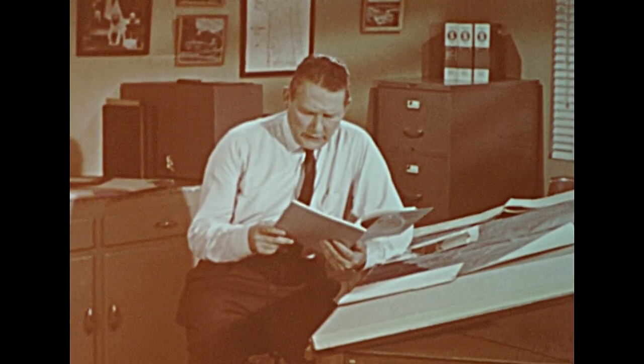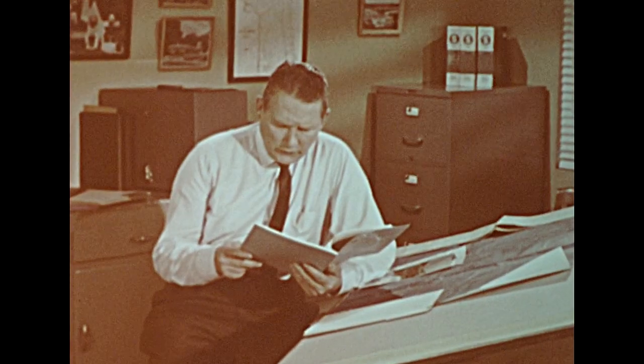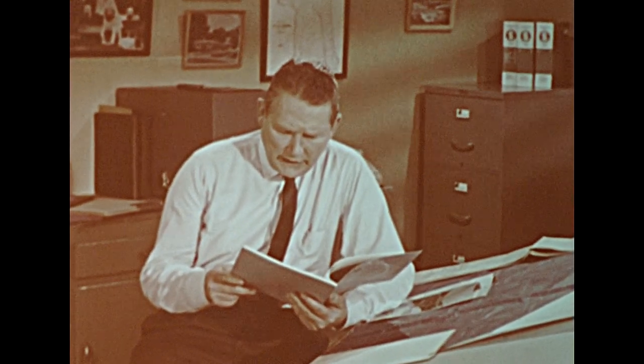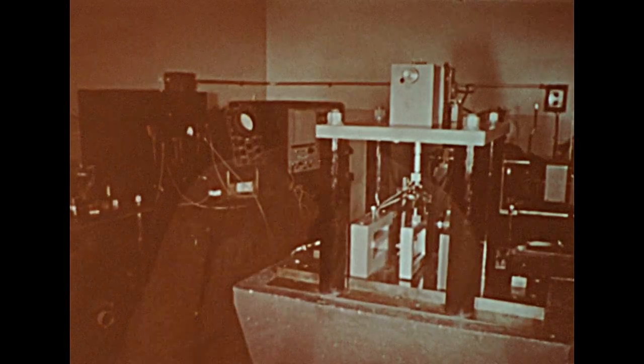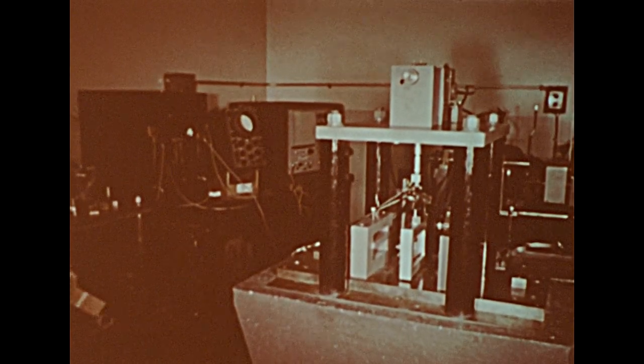The test program, carried out on assemblages 3 to 6 months old, showed definite differences in the mechanical responses of the assemblages. Basically, the early indications from these tests are that the high lime mortars have superior ability to adapt to mechanical strains and dimensional changes in the structure. That is, have greater flexibility and resilience. Well, that's pretty technical, but fortunately, we also have motion pictures of these tests, which make it somewhat easier to understand. Here's the equipment they spoke of in the report.